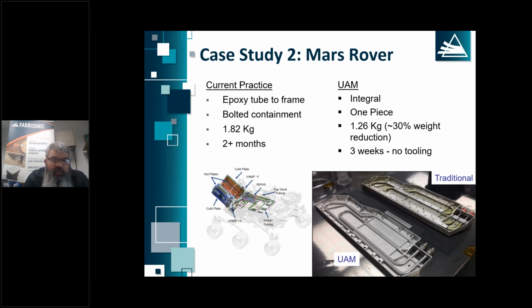The bottom right picture kind of shows a comparison of the traditional way of making a heat exchanger for some of these interplanetary vehicles. What historically has been done is taken a piece of billet aluminum, milled some sort of ortho grid, and then they actually take a Sawzall and cut out some of the ortho grid, and then they go in and epoxy a stainless steel tube onto the aluminum, and then they cap that with an aluminum saddle, again, epoxied in place. So you can imagine that the epoxy is not that great for thermal conductivity, and all of the bolts and all of the saddles add a considerable mass to the process.